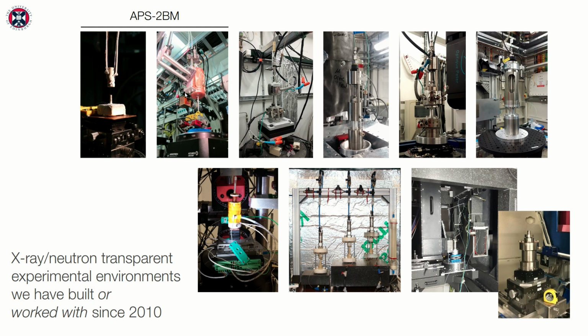But clearly only varying the temperature is, for geoscientists, not really very satisfying in the long run. So in about 2012, 2013, I started to essentially pester people to help me build a first core holder, an X-ray transparent core holder that would allow us to also apply confining pressure to a sample, and this is a much evolved version. I'll show you more of that in a second.